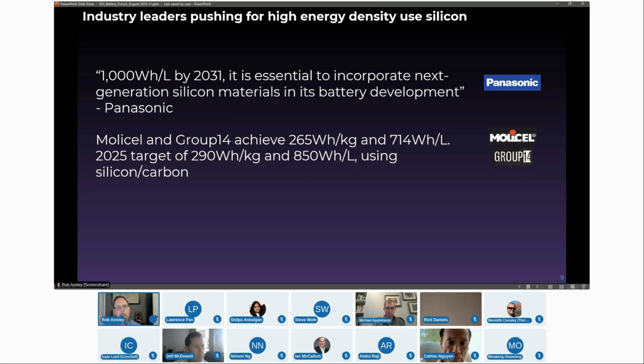Well, where is silicon carbon composite today in search of that? Well, Molicel and Group14 came out with this amazing new cell that Molicel announced at AABC Europe. And this is a power cell that has really fast charging, really high power, and it hit about 265 watt hours per kilogram and 714 watt hours per liter, about 10% better than a Panasonic state-of-the-art today.